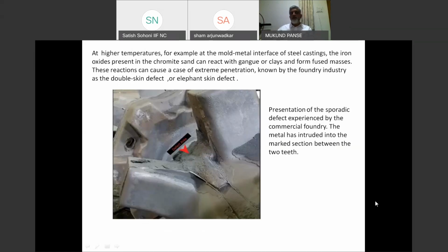This is a photograph of the chromite sand used and fused at a heavier junction because of reaction with silica and iron. This is called double skin defect or elephant skin defect, and this can then be removed only by chipping. Even by grinding it is difficult because it is a hard refractory mass and doesn't get ground. Fettling becomes a major issue if this sand layer is formed.